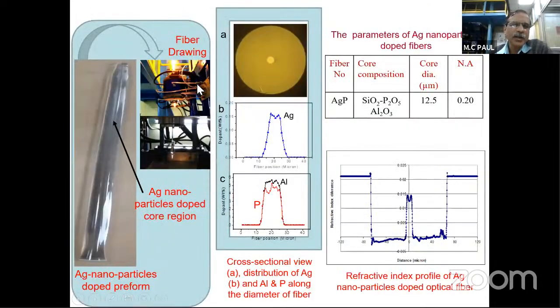This is basically the fiber we made, where this is the core region where silver nanoparticle doping is fabricated, and this is the silver-doped fiber. This is the microscopic view of the fiber. This is the distribution of silver along the diameter of the fiber. This is the distribution of phosphorus and aluminum along the diameter of the fiber. This is the EPMA analysis.